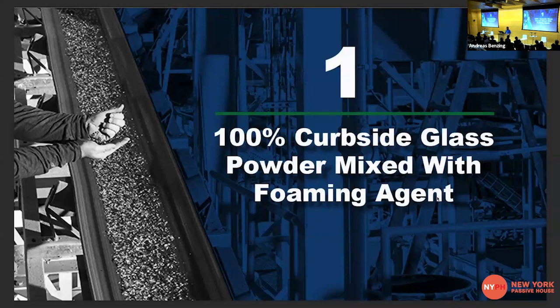This is soda lime glass. So we're taking the glass that's already been used, bringing it in and saving it from the landfill. We clean it, and once it's clean, we get the LOI proper. Then we're adding a foaming agent to it. 98% of the matrix is the glass flour, and 2% is a foaming agent. The foaming agent we use is silicon carbide. We get the silicon carbide from recycled solar panels. So we take recycled solar panels and grind that material up. We have silicon carbide.